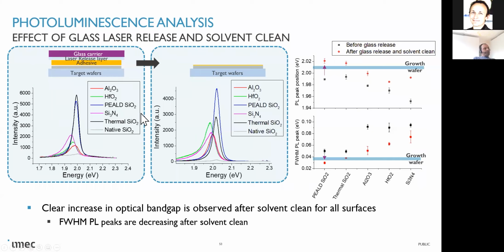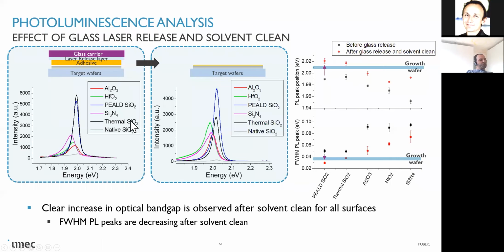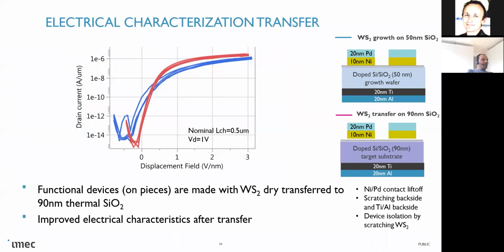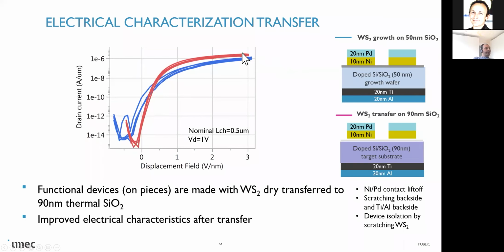What we also see and learn is that depending on which substrate you're transferring to, there is another way of strain buildup in the layer. And this is also something that we still need to further investigate to better understand. The good news was that when we do the transfer, we make very simple devices on top of the directly grown layer, the blue one, and we compare that to the transferred layer. We see that we even gain some performance of the material after transfer.